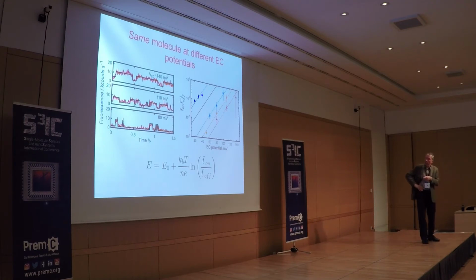And what you see here, if you keep the voltage constant, for three different values of voltage, is the on-off. The molecule is now switching between oxidized and reduced, oxidized and reduced. And of course, it's doing this automatically. You don't do anything there. You just have to record the statistics. You measure these long traces, and then you do statistics of the time when the molecule is oxidized and reduced. By measuring the ratio of oxidized and reduced, you get the midpoint potential of your reaction. And what you see here in this plot is a few examples, because I told you the experiments were so lengthy and difficult. It's only a statistic with a few molecules.